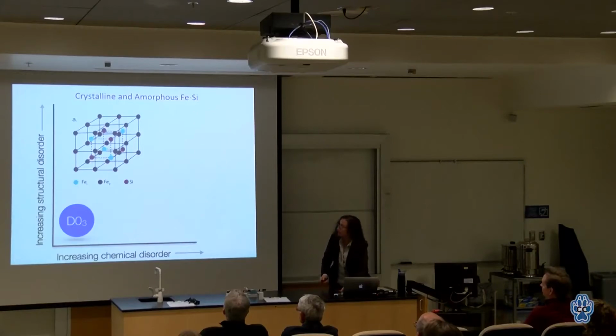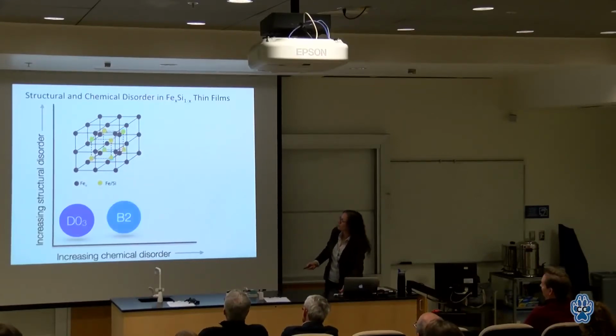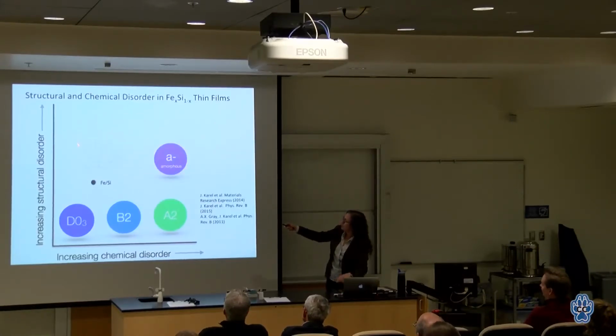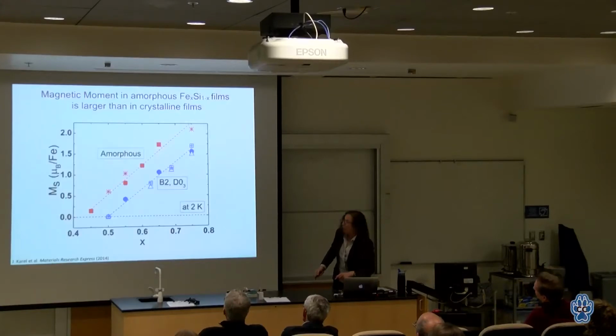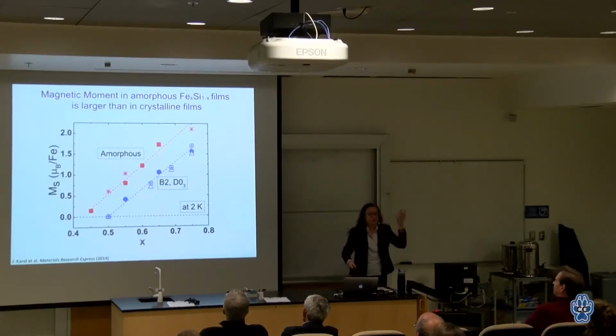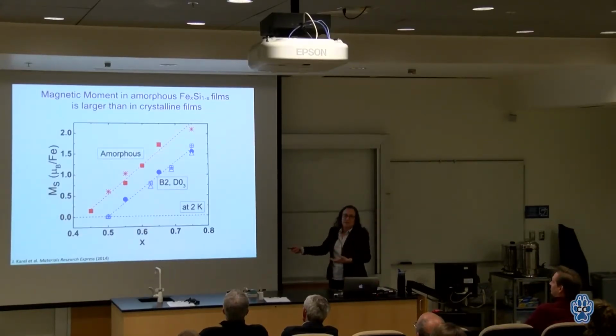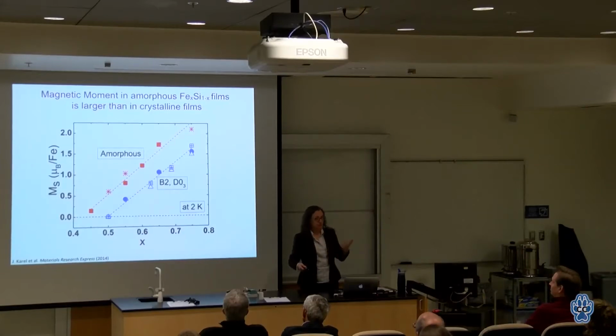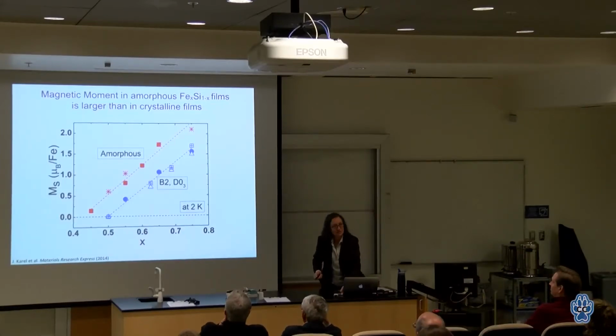I'm going to whip through a couple of other examples and then get back to the silicon. We also looked at crystalline and amorphous Fe-Si. In the crystalline state, you can have different forms of chemical order. And there's my amorphous blob again. One of the interesting things that happens is that in the amorphous state, it's more magnetic than it is in the crystalline state. So again, the disorder is actually helping the magnetism.